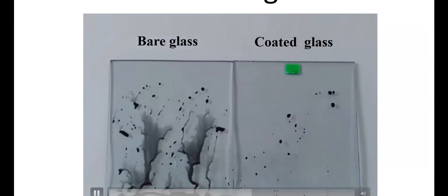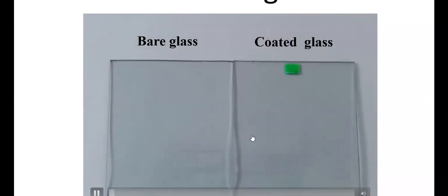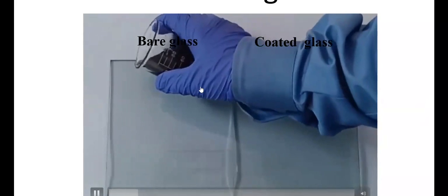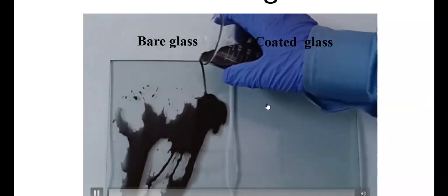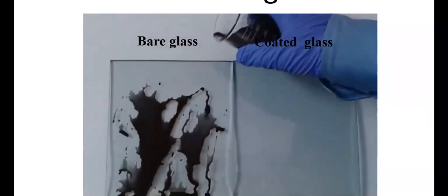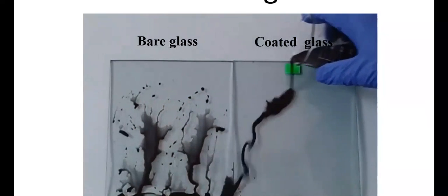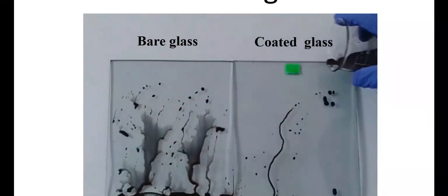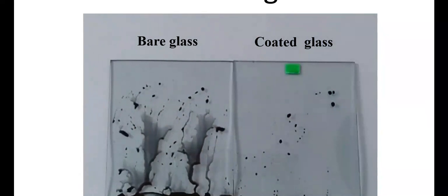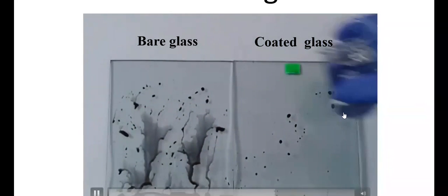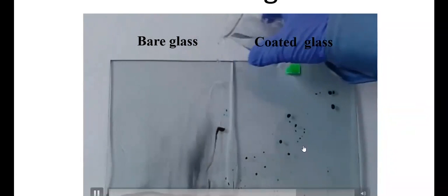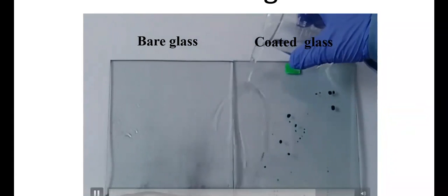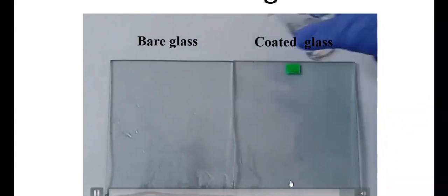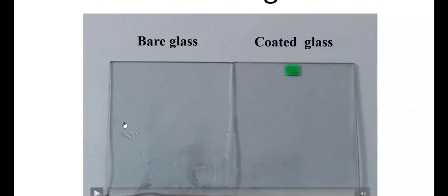Okay, again, here we are pouring mud. This is a mud layer. We are pouring it on a bare glass and also on our coated glass surface. And you see on the coated glass, it is so hydrophobic and it is not sticking to the surface. Over here, it can be washed very easily on the coated surface compared to the bare glass, where it still has the dirt specks over here.